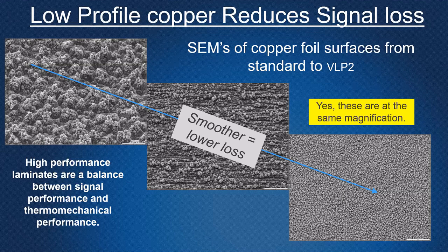Interesting. Okay, so if I'm designing a stack up and I've got something where I need the real smooth copper to avoid losses, I would just drop those down from the top or bottom layers into an internal layer, use the very, very smooth copper till I run it to wherever I need to run it. While on the outside, I'd maintain the thicker layers with the larger dendrites, just to keep everything on the board. Right, and that's very common, to use standard foil on the outside and use smooth copper for the transmission lines, especially in a strip line system where you have a reference plane on both sides of the internal layers. Using the smooth copper inside is beneficial.